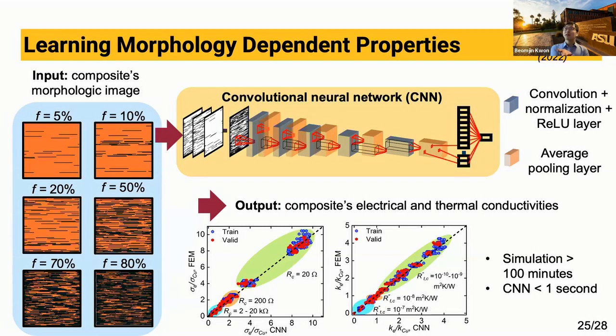And the problem is, if you try to simulate the CNT composites using numerical simulation, it takes a very long time due to the extremely high aspect ratio of CNTs. So we try to tackle this challenge using a deep learning technique. In this method, we employ the composite materials morphologic images as input. Basically, we randomly generated the morphologic images of copper CNT composites having different fractions. Here, the black horizontal lines correspond to the CNTs.